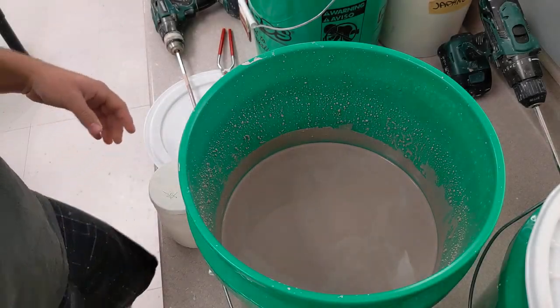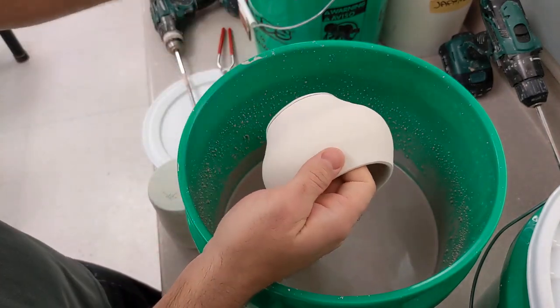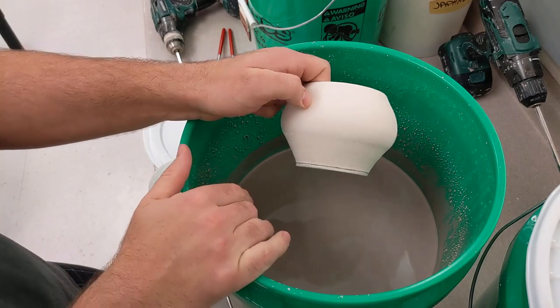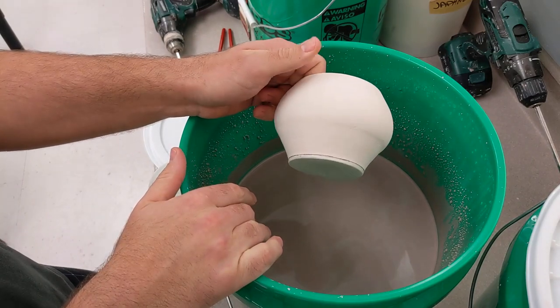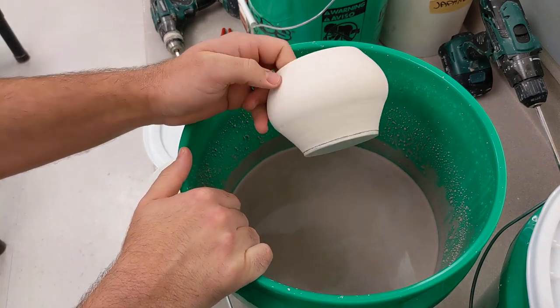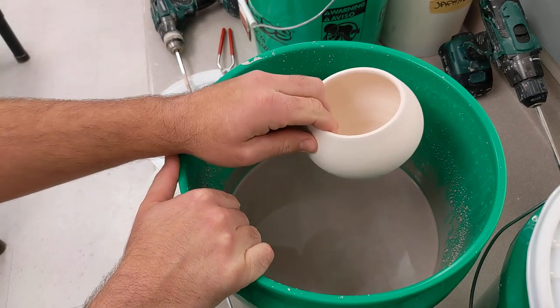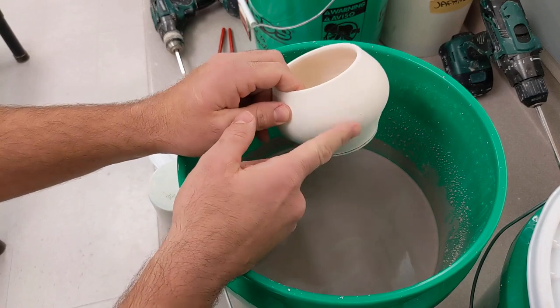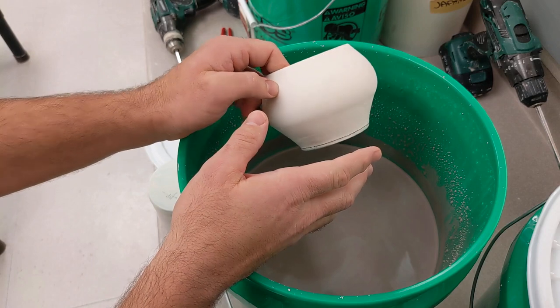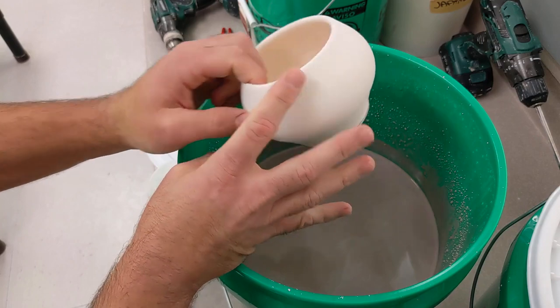I want to show you two different ways to glaze your pieces. Unlike what you've probably done in the past where you brush glaze on, all of our glaze is dipped. You could brush it if you wanted to, but it's not really formulated for that and it doesn't brush as well as commercial glaze. If we do a dip, it needs to be roughly one to two seconds long. Any more than two seconds and you run the risk of your glaze becoming too thick and running down the side during firing — that usually ends up in a lost piece.